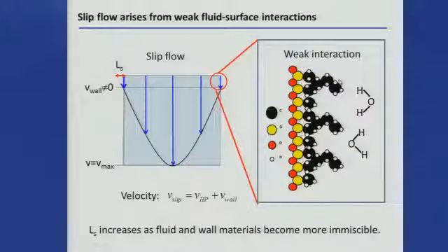So why would the fluid velocity not go to 0? Well, in the chromatography that we do, we have a hydrocarbon monolayer. And so the water does not interact strongly with the hydrocarbon monolayer. And so why should the water stop? There's a force being applied from above here by the fluid, and so it will keep going, so there should be some non-zero velocity. And so Navier called that slip flow.